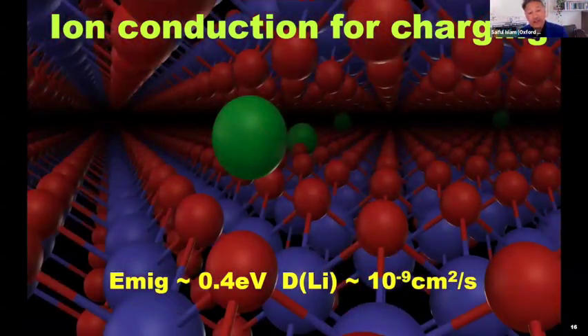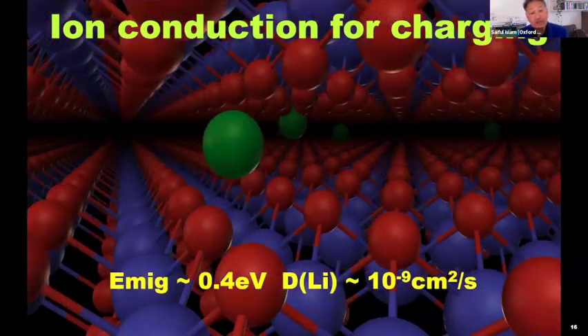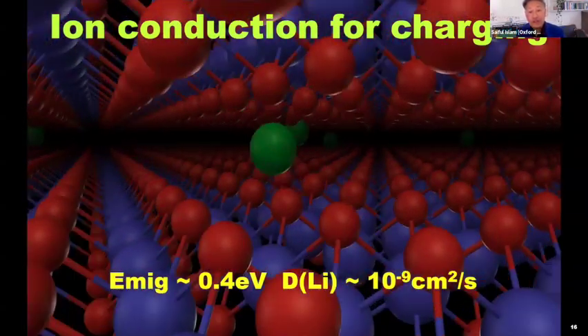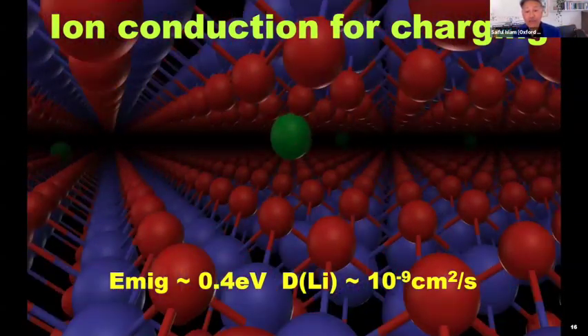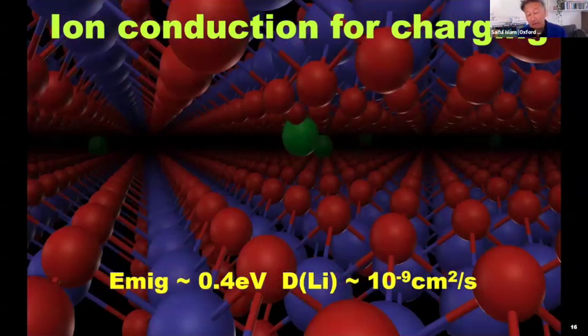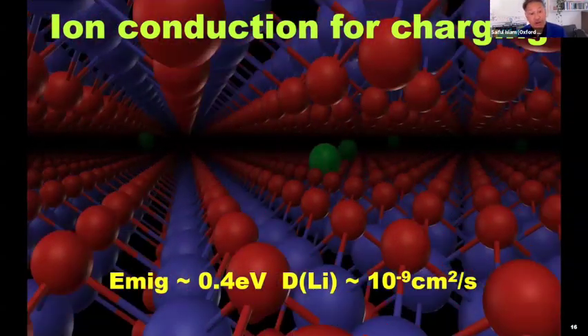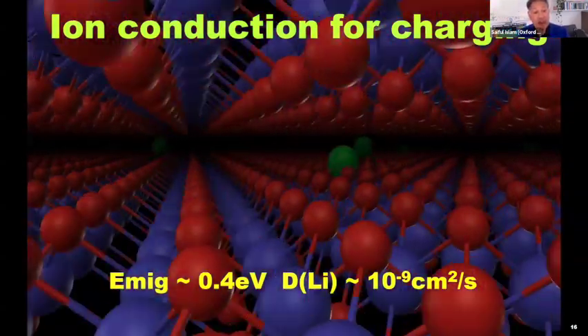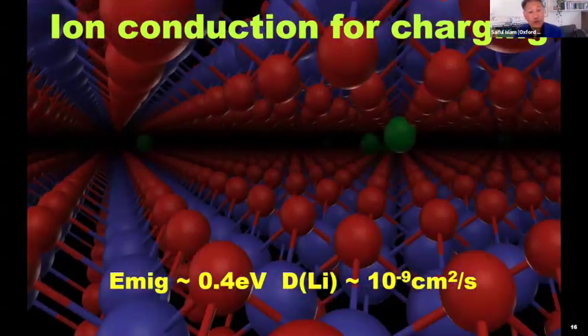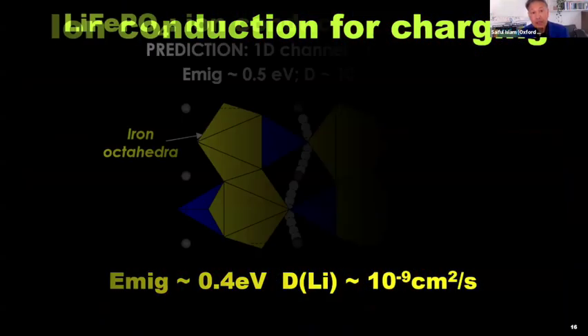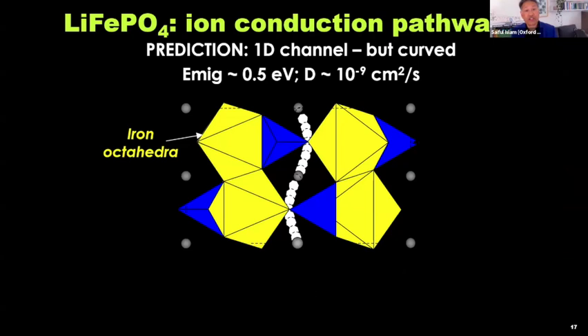We can, from modeling, derive what is called a diffusion coefficient, which is 10 to the minus 9 centimeters squared per second for this material. And the activation barrier is about 0.4 electron volts, 40 kilojoules per mole. We can do this for other materials, and this is the lithium iron phosphate. What I'm showing you here is a slice through the crystal.